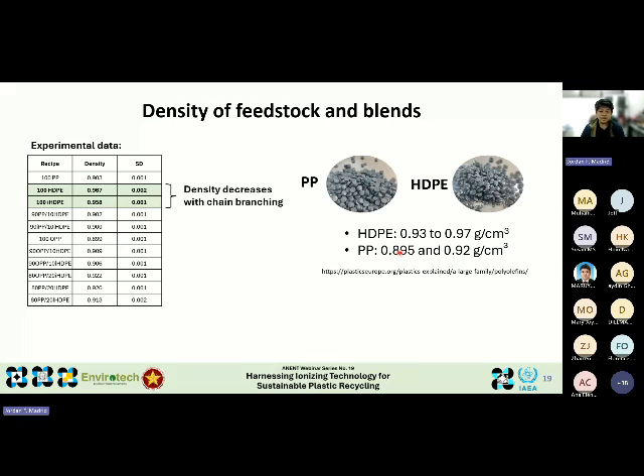After electron beam irradiation, the density of the high-density polyethylene decreased from 0.967 to 0.958. This is consistent with the idea that branching was introduced into the material. Take note: there's no cross-linking, or very minimal cross-linking here, as we've proven with the gel fraction experiment.